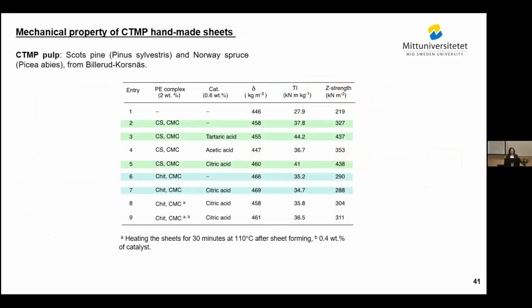For this, we chose the CTMP pulp. And here in entries 2, 3 and 5, we can see that adding a catalytic amount of tartaric acid or citric acid improved the Z-strength and the tensile strength compared to without adding catalyst. But in another experiment, instead of cationic starch, we chose chitosan. Also, we see that chitosan and CMC improved the property, but the effect of catalyst here is not clear.